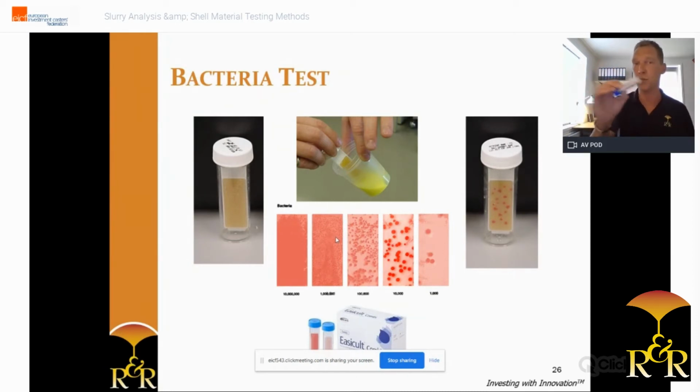Again, you need the centrifuged binder, which needs to be really clean, because if there's any residue of the refractory present in it, it will cover the strip and it will make it more difficult to read it off. I have the best experience with these Easicult Combi test strips, because they can test both bacteria and fungi in quite a reliable manner.